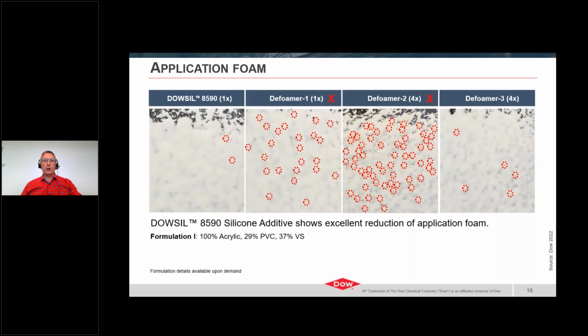We can see that defoamer number 2, which, if you go back to the other slide, was showing a good appearance of drawdown, has the highest level of bubble formation when the paint is applied using roller. Mineral oil defoamer, competitor defoamer number 3, does present a lower level of defect formation, similar to the featured material. But as a reminder, this material required 4 times the amount to achieve this performance and resulted in a decreased gloss level in the drawdown film.